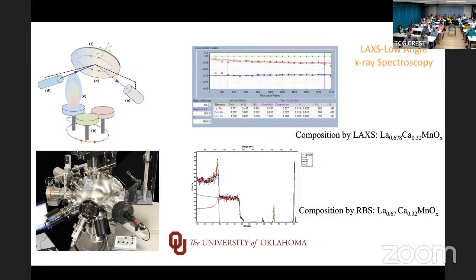So in my company, we developed a very novel algorithm to extract composition information from this. As we grow the film, for example here, the composition comes out to be lanthanum 0.678, calcium 0.32, manganese O_x. That's a film that we made, and that's an in situ composition measurement.